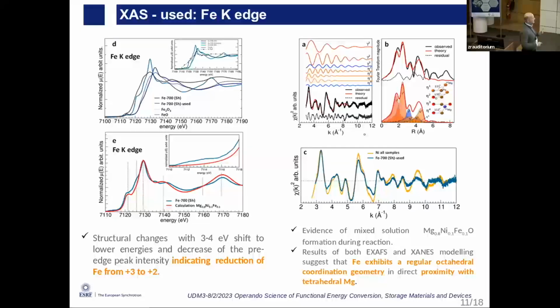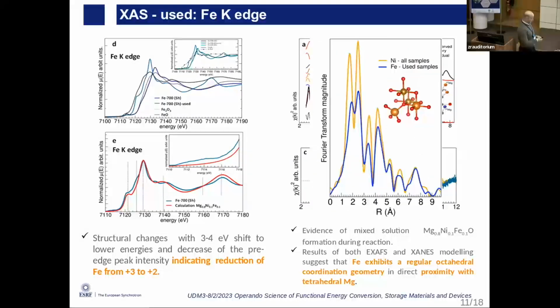From the EXAFS analysis, if you look at the K-space, the iron basically has the same environment as the nickel. It seems to be more disordered, and this is also clear from this kind of comparison.